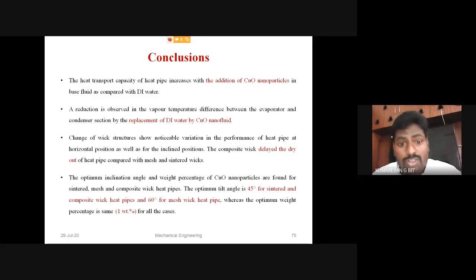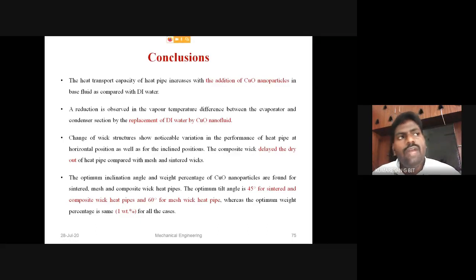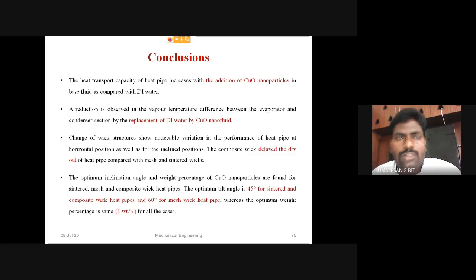Then the change of wick structure shows noticeable changes; there is a variation in the performance of the heat pipe at the horizontal position as well as at the inclined positions. The composite wick delayed the dry-out condition of the heat pipe compared with the mesh wick and sintered wick heat pipes. This is because when we combine the sintered and mesh wick heat pipes, the porosity values increase as compared with the mesh and sintered wick heat pipes. Additionally, the optimum inclination angle and weight percentage of the copper oxide nanoparticles are found for the sintered, mesh and composite wick heat pipes.